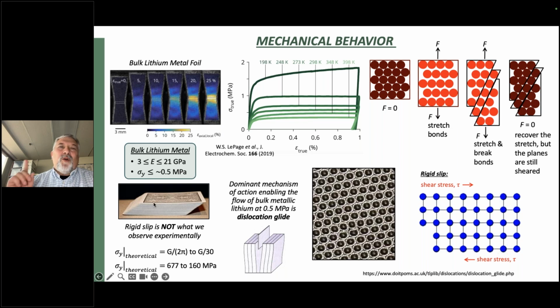That mechanism is the wrong mechanism of action. We know it's the wrong mechanism because the theoretical yield strength associated with rigid slip, that's calculated here, these numbers are orders of magnitude higher than what we observe experimentally. So that's telling us, hey, you got the wrong mechanism there.